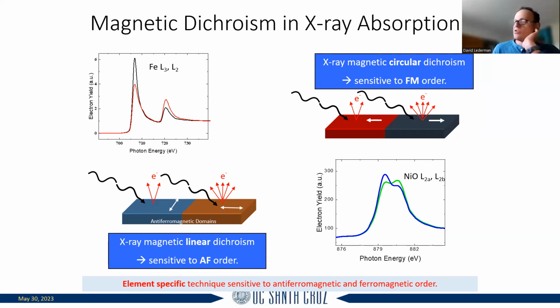Unfortunately, you do need a synchrotron. You need to have access to a synchrotron. So we had collaborators at Stanford and at Berkeley, where they have their synchrotrons, and they were able to do this measurement. What happens is you take circularly polarized X-rays that you tune to the L absorption edge of the transition metal. Then you measure with the right-handed and left-handed polarizations, and the asymmetry that you might see, something like this, tells you that there is something that's ferromagnetic.